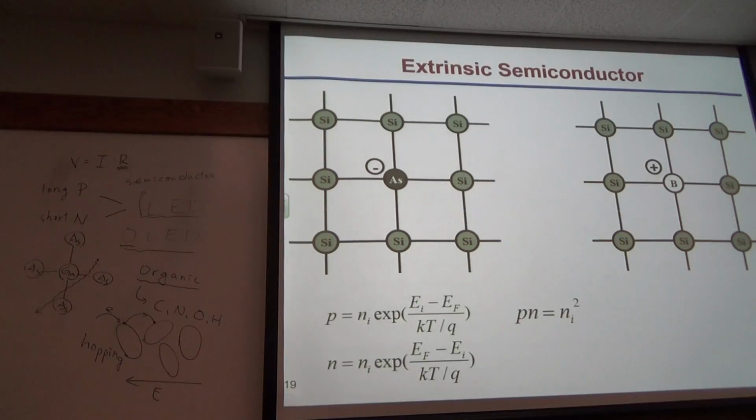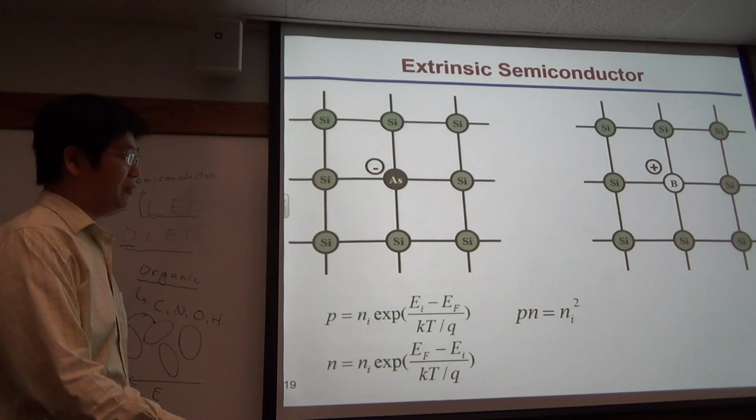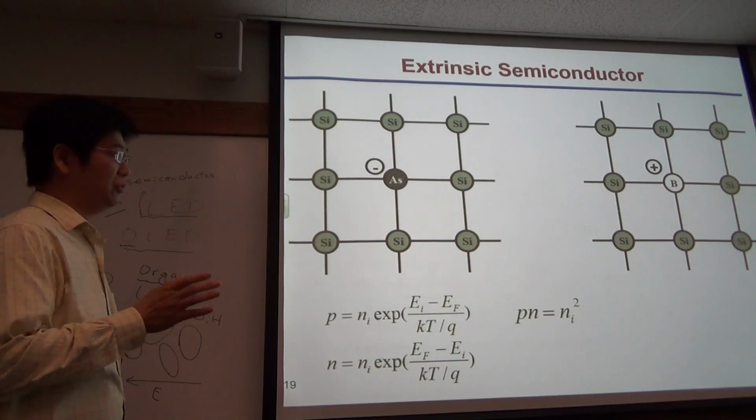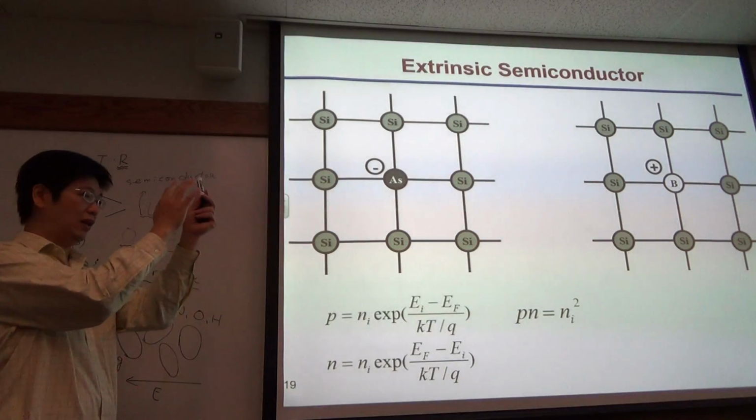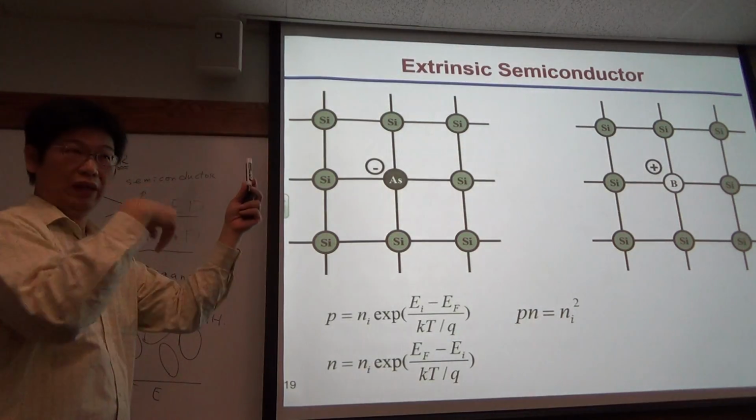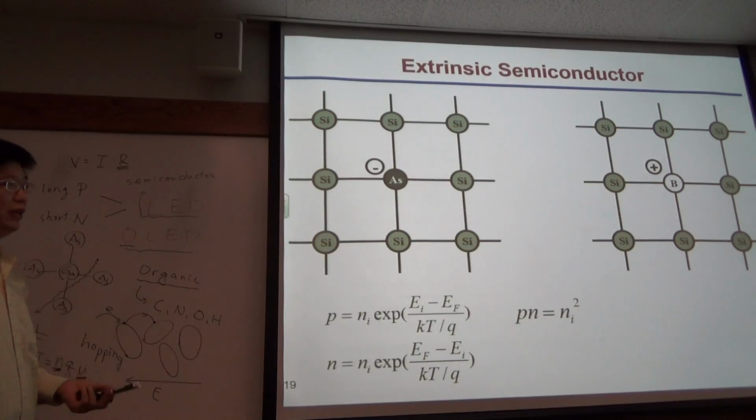So the other way: resistivity is inversely proportional to conductivity. And conductivity equals nqμ. Last time, last week, we wrote it down here, right? If we have dopant, we increase the carrier concentration. The other way is to increase the mobility, so the carriers can move more easily. At that time, maybe 1970, they tried to make single crystal organic material, aligning the organic material so that electrons can find a channel to go through. That's good. From 1,000 volts, it went down to maybe 100 volts or so. But that is not enough, because right now we need less than 10 volts.